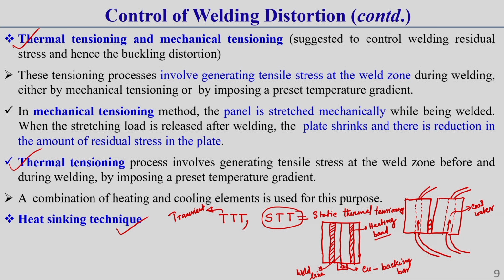So, by this heating band here, generally we use a range of heating. That means this range of heating can vary from 100 degree centigrade, then 200 degree centigrade, then 300 degree. So, different types of temperature range we have to heat in this region, and below this weld there is a copper backing bar through which generally water is circulating. So, one is the cooling effect we are providing, as well as at the side we are using some heating effect.